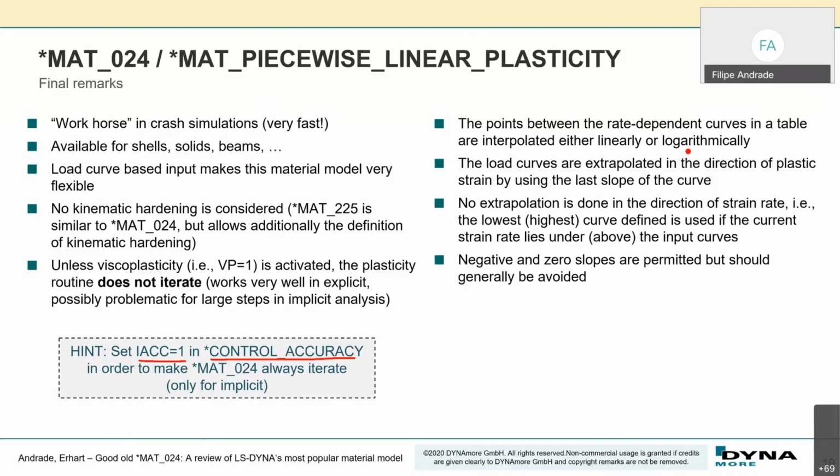Extrapolations are always linear, using the last slope of the curve. One thing that I didn't mention is that there's no extrapolation in the direction of strain rates. It doesn't matter which direction. The lowest curve and the highest curve will always be the limit of your